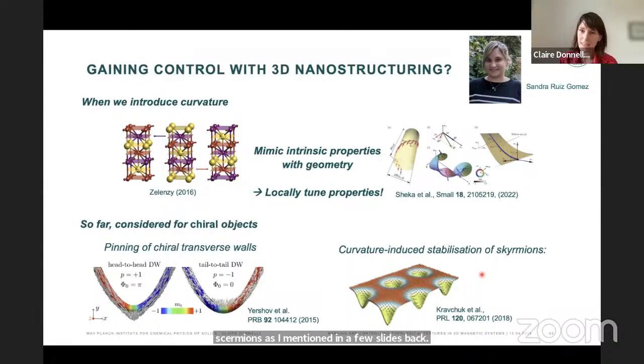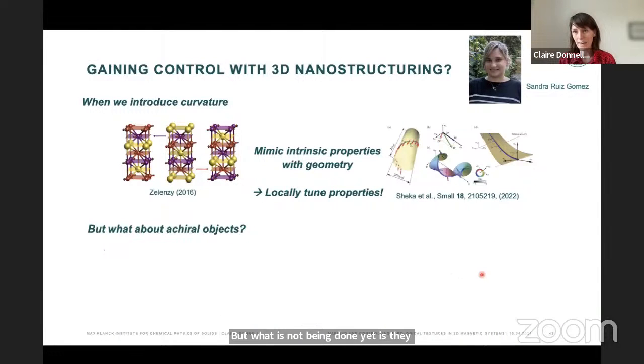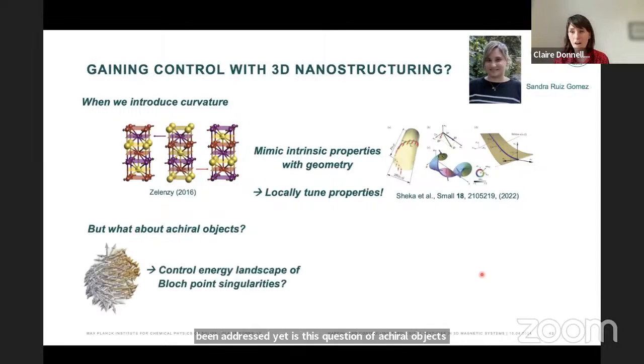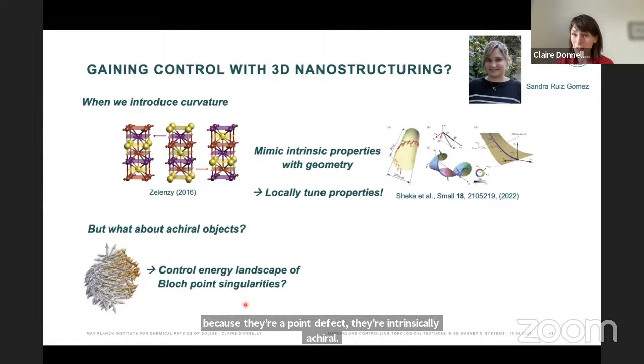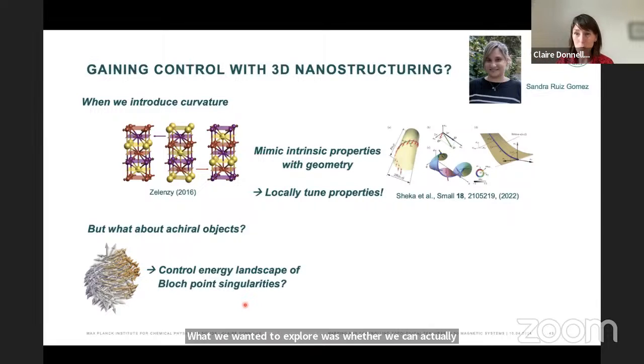But what has not been addressed yet is this question of achiral objects. What we're particularly talking about here are these point defects, which correspond to these Bloch point singularities in the magnetization, so these topological defects, basically. Because they're a point defect, they're intrinsically achiral. And what we wanted to explore was whether we can use this curvature and curvature-induced symmetry breaking to change or tailor the landscape of such singularities.